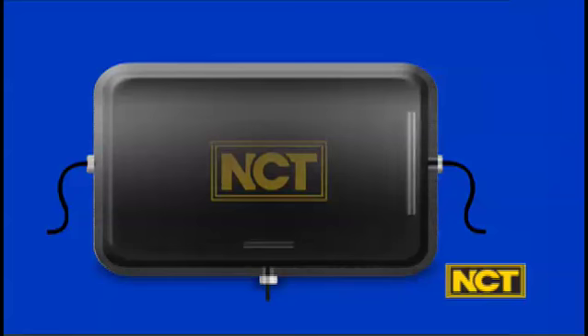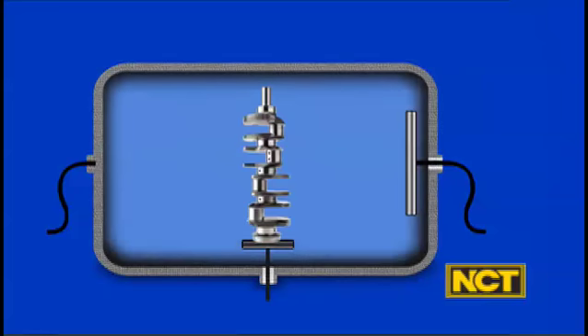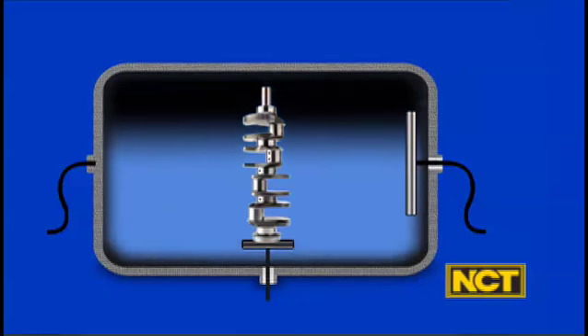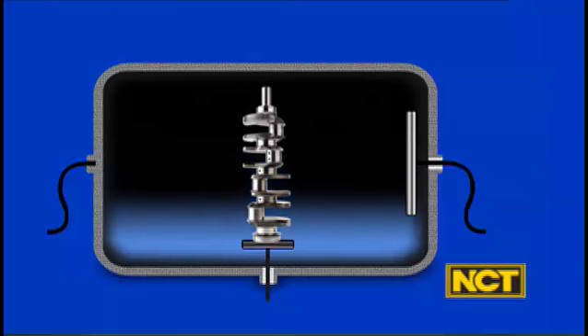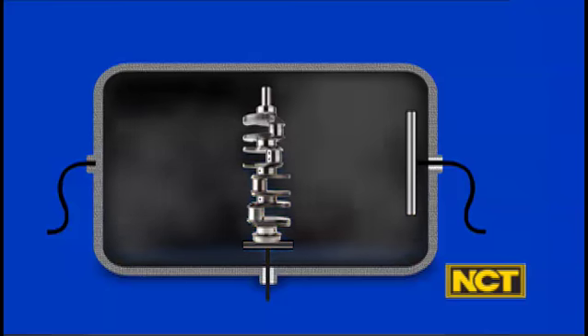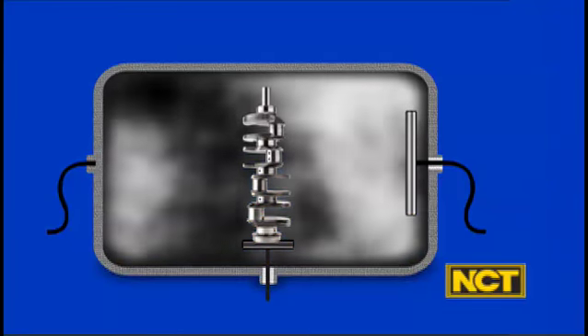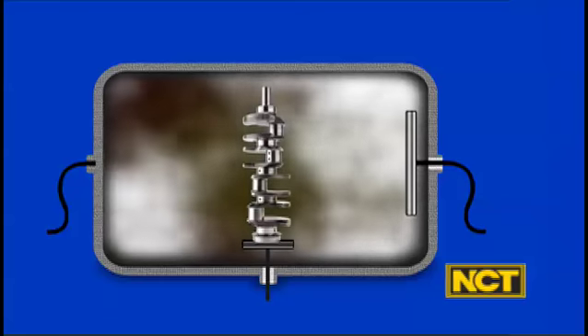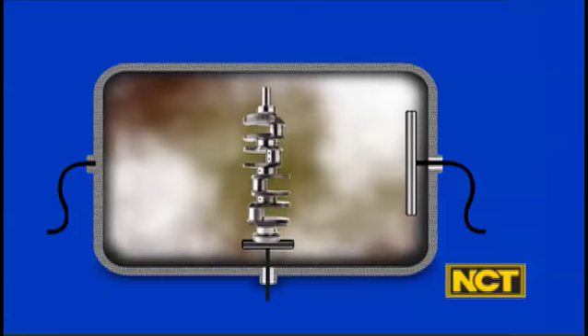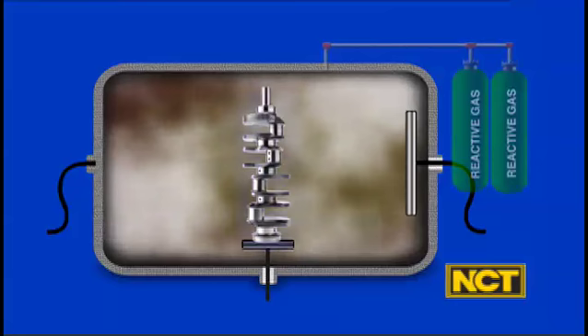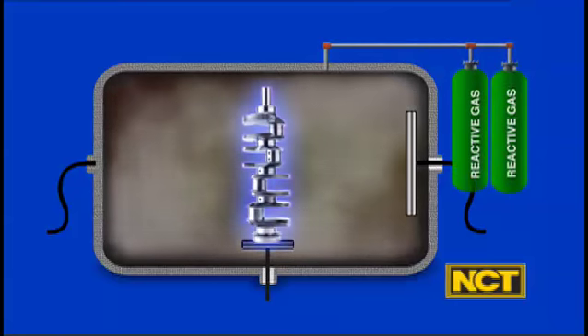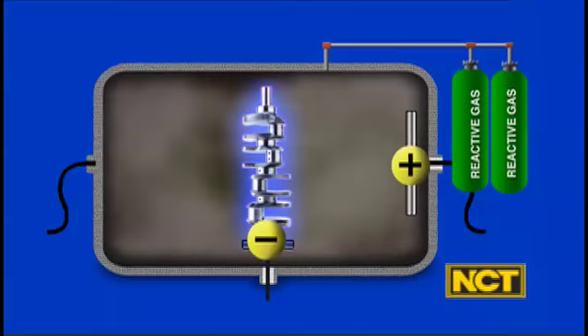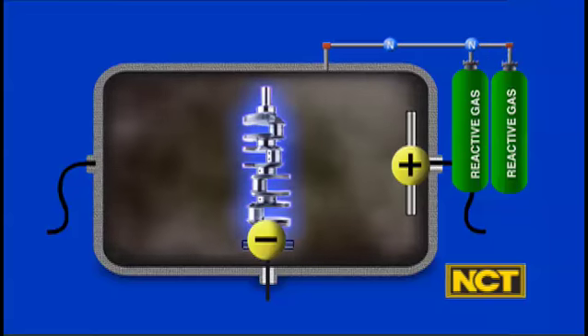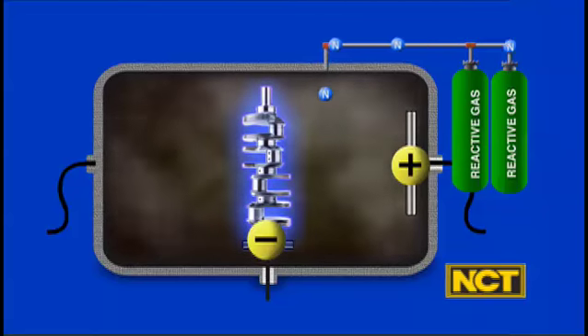With plasma ion nitriding, components are placed into the chamber and the atmosphere is removed. The chamber is then backfilled with a hydrogen gas and the components are heated to between 900 and 950 degrees Fahrenheit. A plasma is generated by an electrical charge that is applied to the components. A gas mixture containing nitrogen is introduced and the nitriding cycle begins.